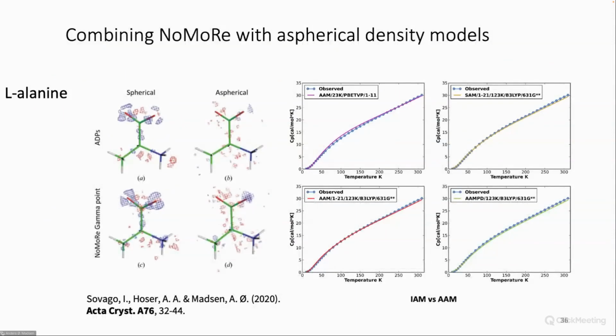Okay, just a few words about the latest developments that we have here. With our normal mode refinement, we have already looked at how we could incorporate aspherical modeling of the electron density into this normal mode refinement. And we used the XD charge density refinement program, or multipole approach, to look at L-alanine at several temperatures. And what we could see was that once we start using these aspherical models, we can remove some of the residual electron density from the bonding region, but we are not fully satisfied, I would say, with the resulting electron density.